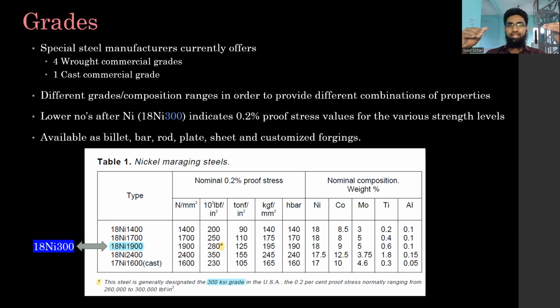Another thing is 18% nickel is critical, as I highlighted in the initial part of the slide. Nickel is not very much. Its portion is the same, 18%, and it is critical. Why? Because it heavily lowers the martensite start temperature. The start temperature of martensite is heavily lowered because of it. And we have discussed that the objective is to have a high Ms temperature. That's why nickel is critical.